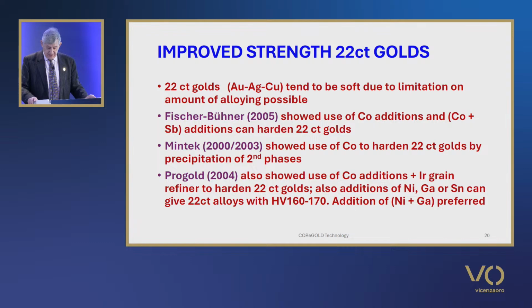Similar work has been reported by Mintek in South Africa. In their 2000 paper, they reported on a new hard 22-karat gold alloy, but gave no details of its composition. It has a colour similar to conventional 22-karat gold, but can attain a peak hardness of 274 Vickers in the cold rolled and aged condition. However, in a later paper in 2003, they describe work on both 99.5% gold and 22-karat gold, that's a gold, copper, silver alloy, in which they study the effects of alloying metals cobalt, germanium, antimony, zirconium and vanadium in hardening them. There they report a maximum hardness of 274 Vickers after cold rolling and aging for a